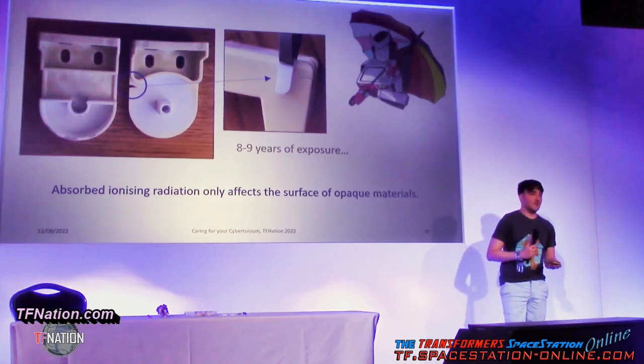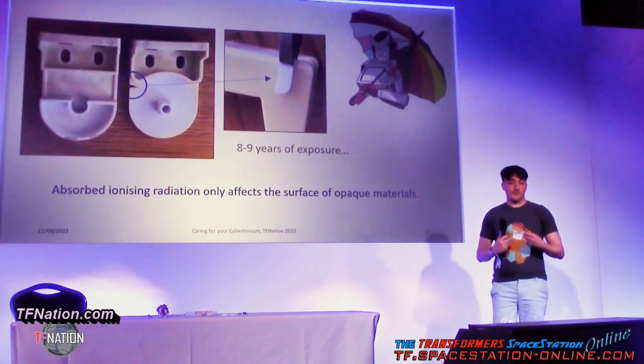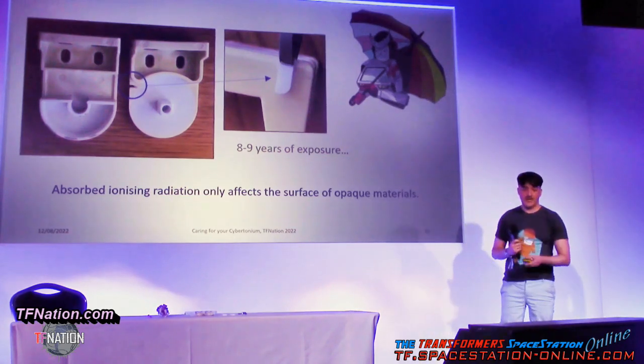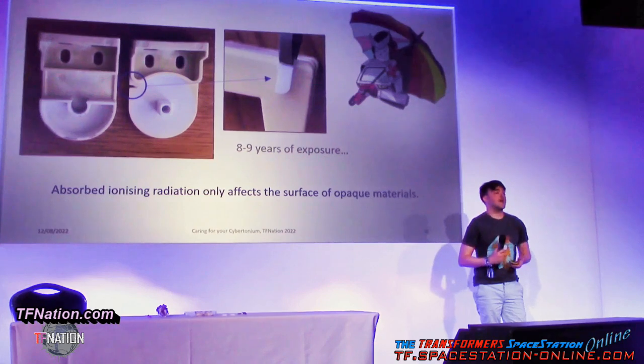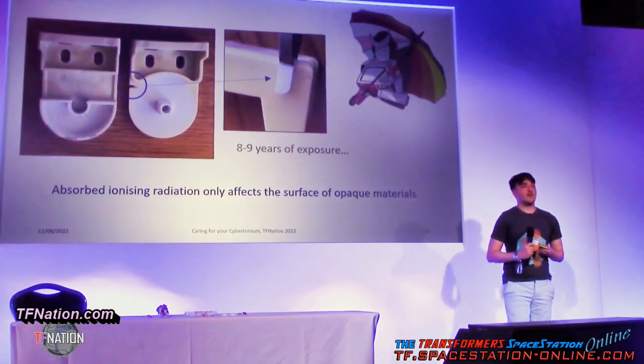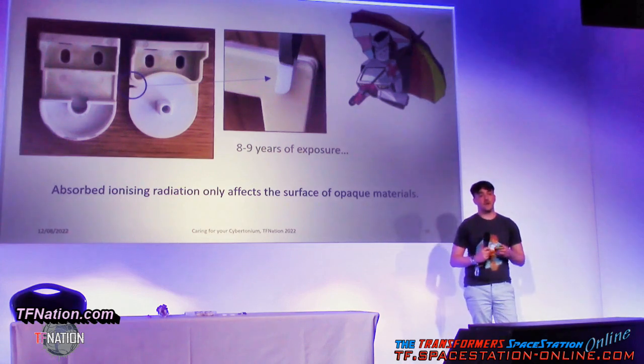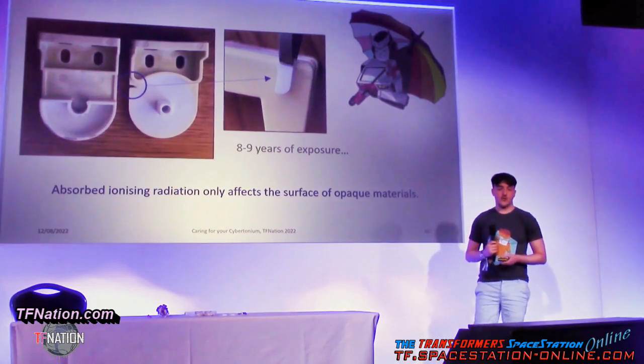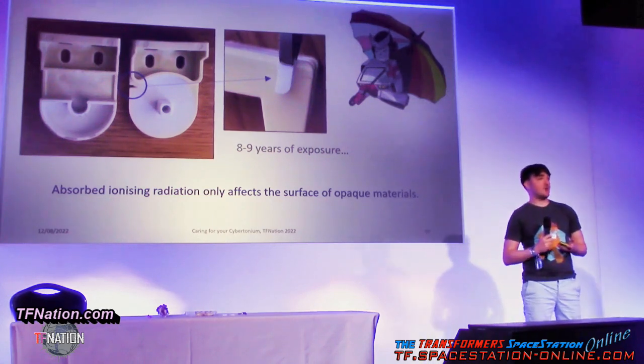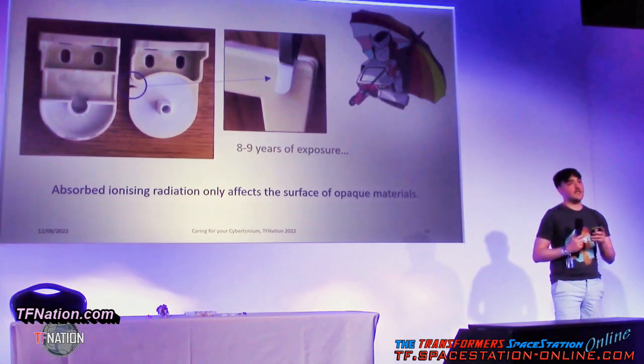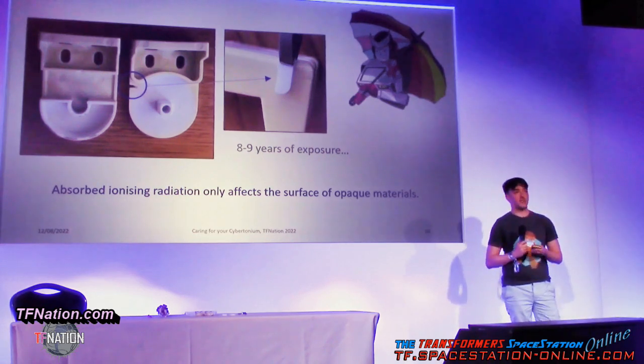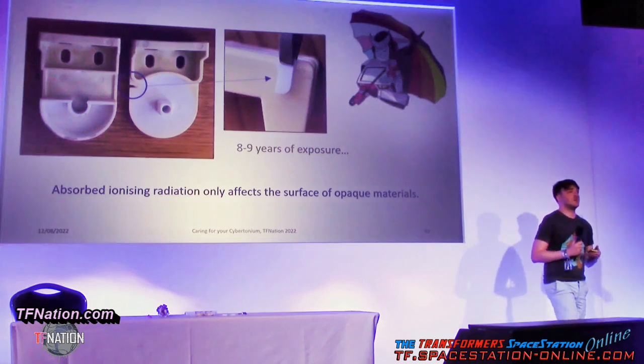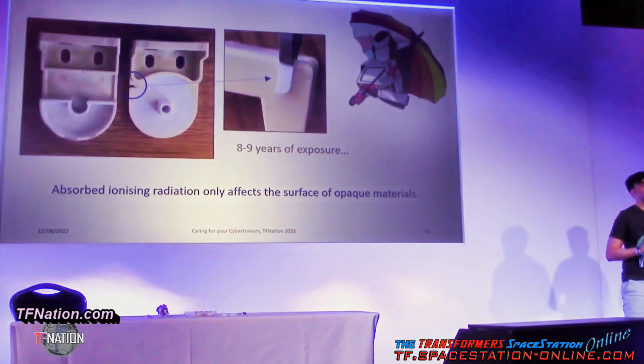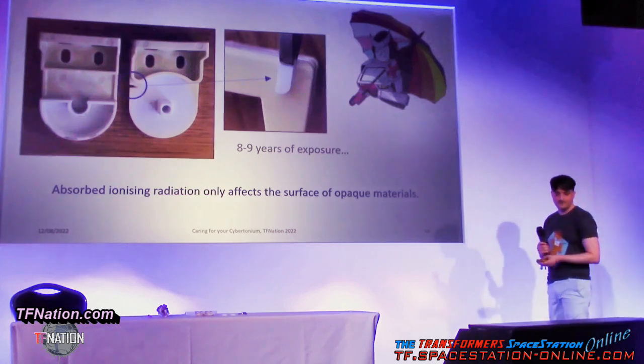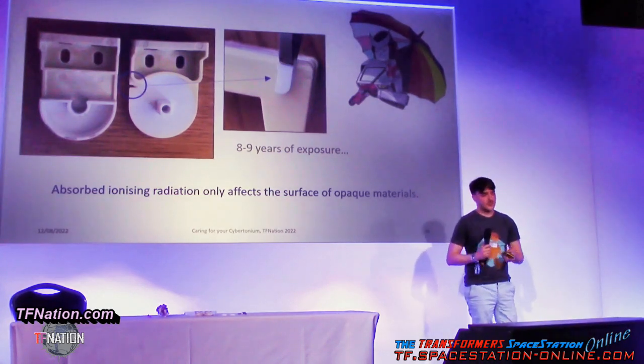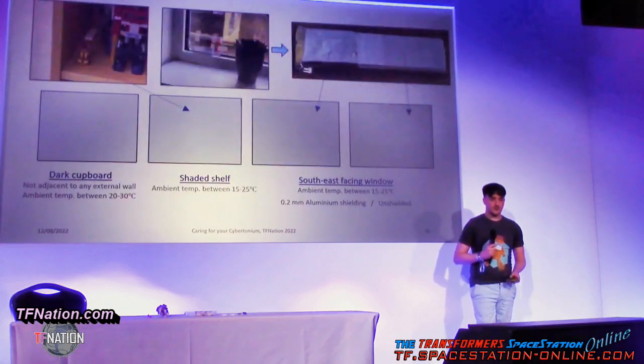Well, I would say never keep a transformer on your windowsill. But more importantly, I took a section from it, and cut out a little bit. Ionizing radiation and UV only affect the surface layer. It can't penetrate at all. It's a matter of microns or less. So the section which I cut out, you can see inside it's actually perfect still. You can't even with the eye see the thickness of that sunburnt layer. It's so thin. This is why some people might suggest to you that to remove yellowing you can abrade. And yes, that will work, but you'll change the form of the plastic. Yeah, so at this point it was about 9 years of exposure. So it's quite a good amount.